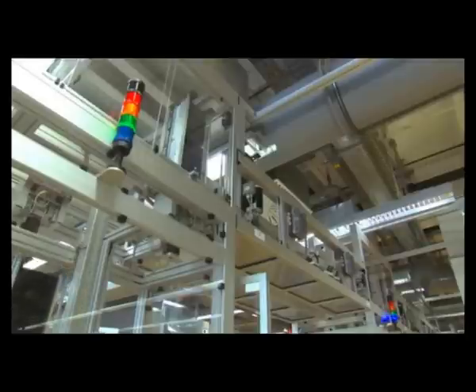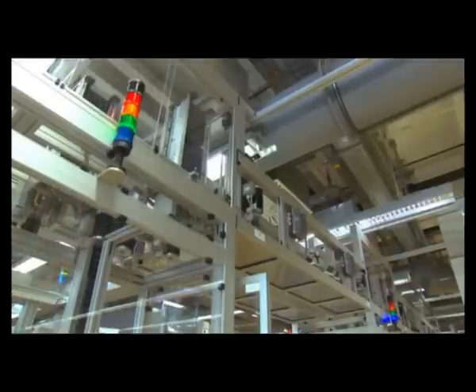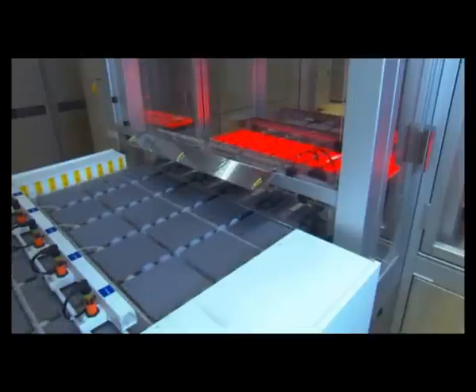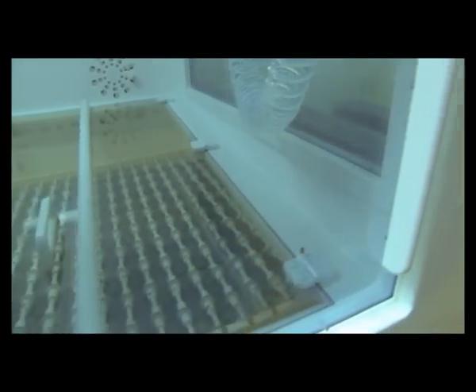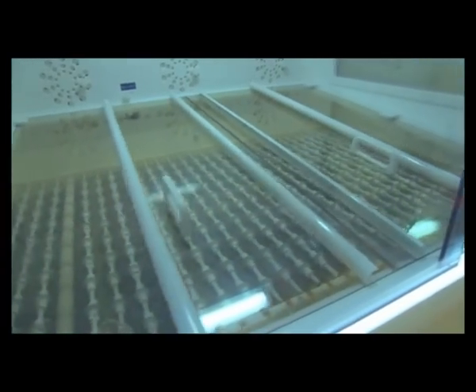However, before you can actually take advantage of this effect, further production steps are necessary. Once again, the cells are cleaned and etched under the scrupulous supervision of our staff. The 0.2 mm thin cells are then placed in an acid bath, where only their bottom and edges are exposed to the acid. The effect: the positive side, the bottom, is electrically isolated from the negative side, the top.